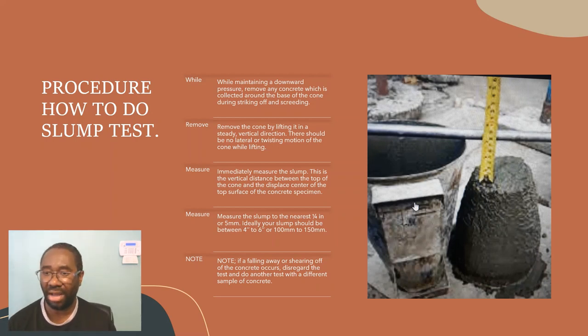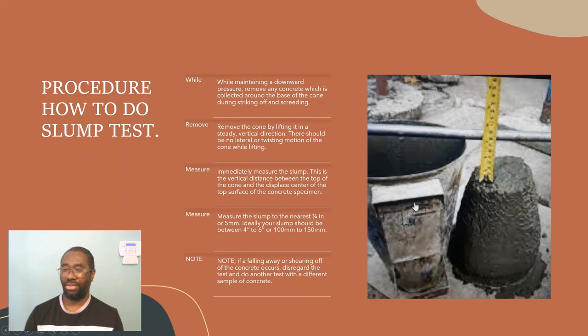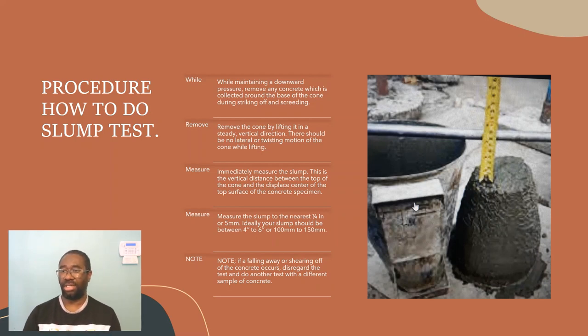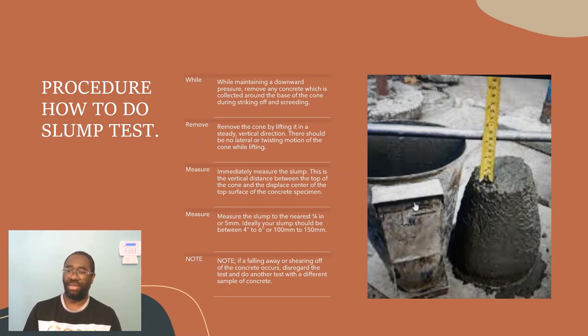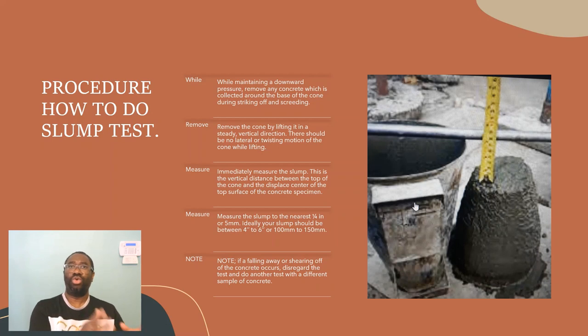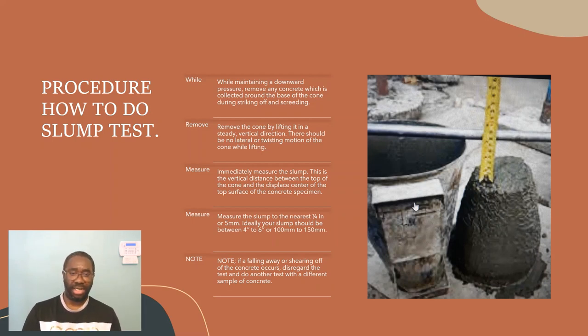If you look at the right of your screen you can see the concrete specimen below and the rod above — you measure the distance between the top of the cone and the displaced center of the concrete to get your slump. Ideally you want to get a slump between four to six inches, or 100 to 150 millimeters. If you are not getting that reading, use a different concrete sample and carry out the slump test again.